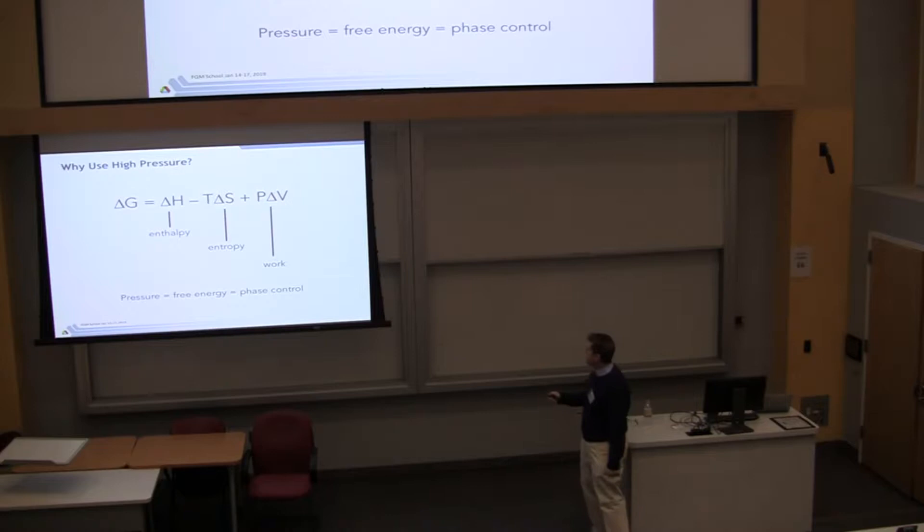Well, sometimes under ambient conditions in your normal lab, you run into walls that you can only dope so far. And it turns out this high pressure can actually allow you to access higher oxidation states of the transition metal and so make this deeper doping possible. I'll give an example of that to verify it. So this is the outline: introduction to floating zone furnaces, motivate why to use high pressure besides those three bullets, give you a physics reason why, a chemistry reason why.